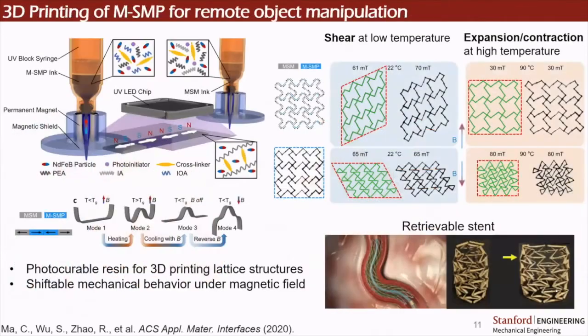Another thought is that we also combine 3D printing and multi-material printing technology to directly print this composite. And we could easily program the magnetization distribution just by changing the printing direction. What we're doing here is applying a magnetic field during printing, and this magnetic field will align the polarity of the magnetic particles in the polymer resin. And then through changing the printing direction, we're actually changing the magnetization direction of each filament. In this way, we can very easily program the distribution of magnetization to give us the desired deformation.